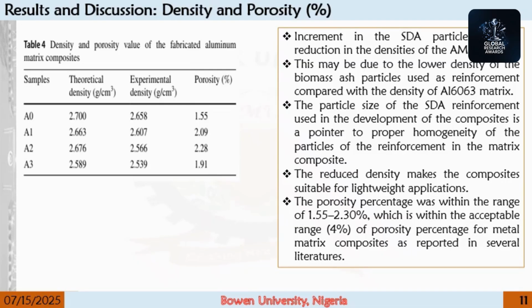And the porosity percentage was within the acceptable range of 4%, as established by several studies like Alaneme 2018 and several other research. Now, it is good to establish that high porosity reduces the strength of the composite and depletes other mechanical properties. So with what we have here being within the acceptable range of 4% for MMC, it shows that the strength of the composite produced here is suitable for lightweight application as envisaged.